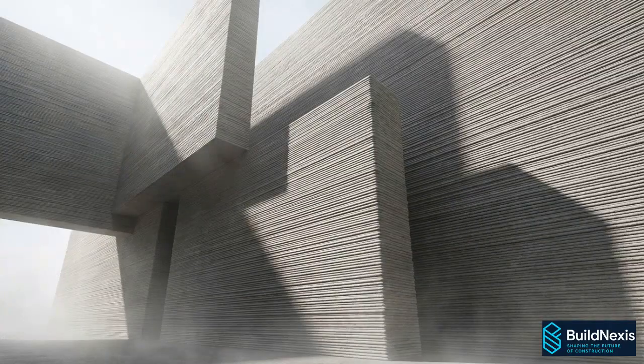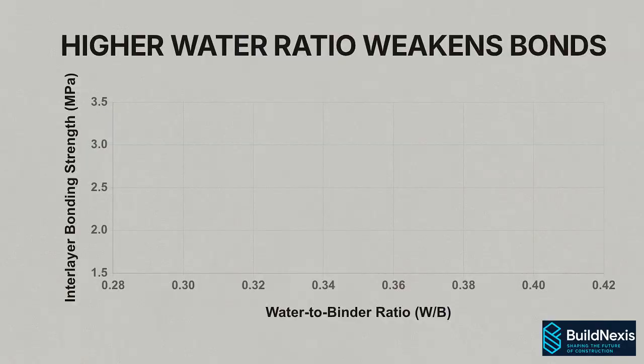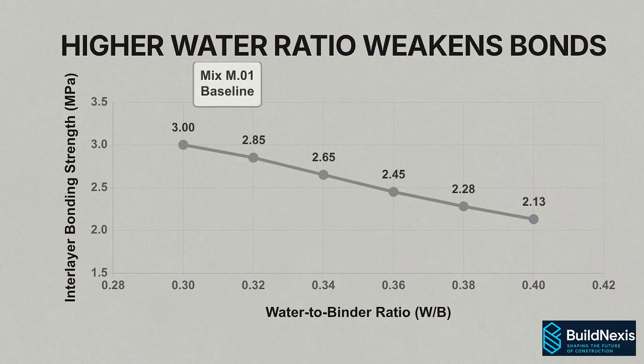In 3D printing, where external physical constraints are absent, the internal capillary pore network becomes the sole governor of geometric stability. The failure sequence is a direct causal chain. High water to binder ratios lead to excess evaporation, driving extreme shrinkage microstrains and interlayer delamination. Across experiments, this relationship remained inversely proportional.